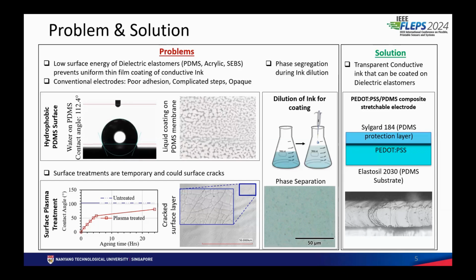There is a way to solve this, which is simply by doing surface treatment or plasma treatment. But for our dielectric elastomers, first on acrylic and SEBS, plasma treatment doesn't really work. On PDMS, it works, but how long it works varies. With time, its surface energy will be lost again. In addition, it can form a brittle top layer, which can crack upon stretching and reduce the reliability of the whole device. So we thought, maybe we should make a form of ink that can be directly coated on this kind of low surface energy elastomers. So this is what we came up with, and this is what I'm presenting today.